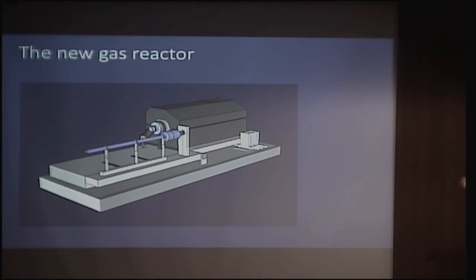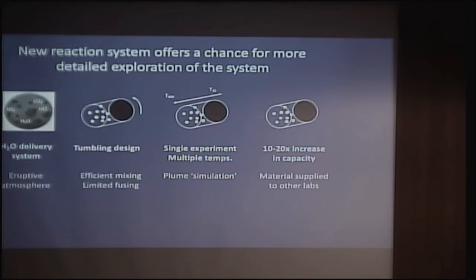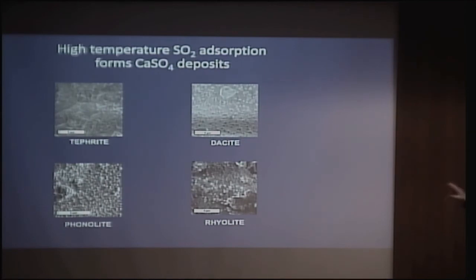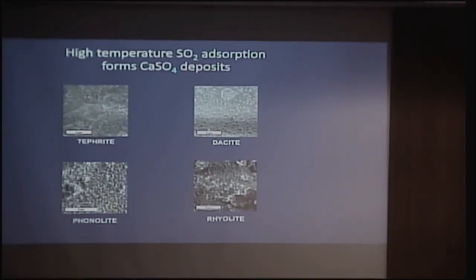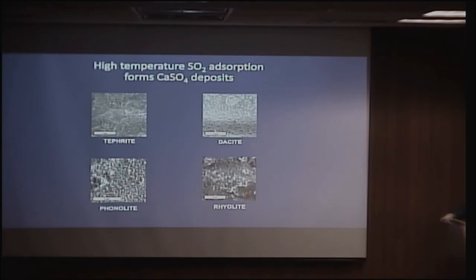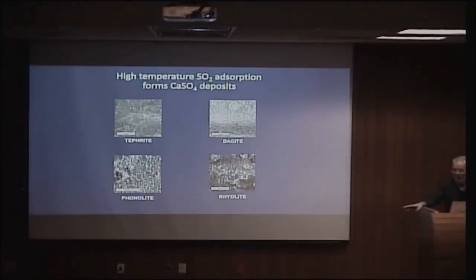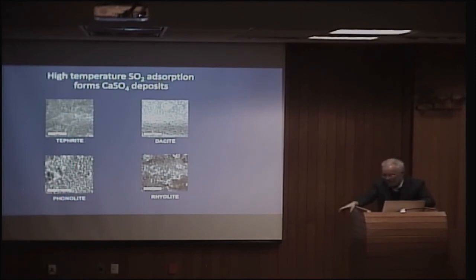We do up to 300, 400, 500 degrees Celsius, these exchange experiments, where we study what the ash does, or what the gas does in terms of depositing components of the gas back onto the ash surface. And we came up with this idea of volcanic sequestration, the idea that you could actually park sulfur in ash deposits and take it out of the atmospheric system, just to be provocative. And we think that you can park up to a half of the sulfur, which is co-erupted with ash, back onto the ash surface and have it fall out with the ash and not be a long-term challenge or a midterm challenge in the atmosphere.